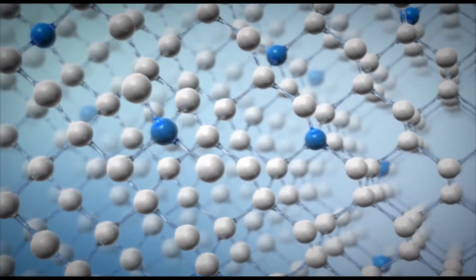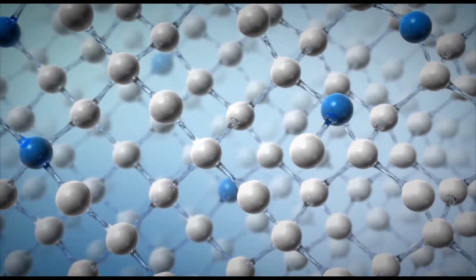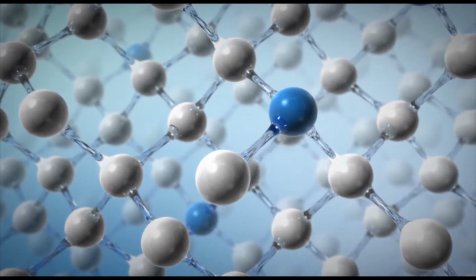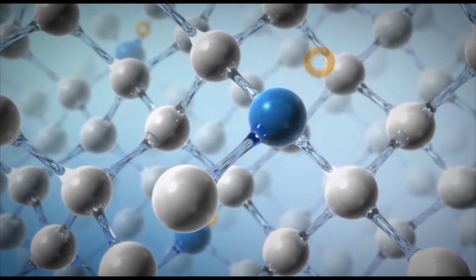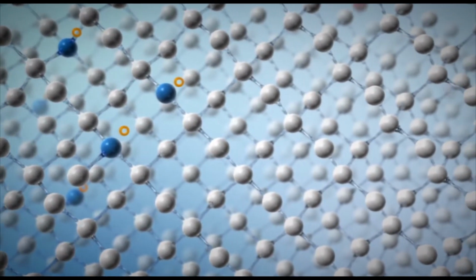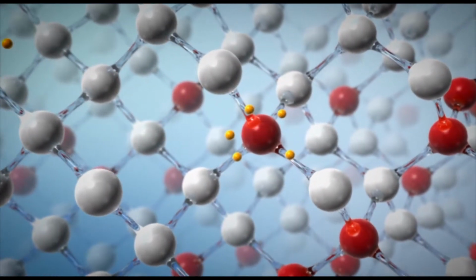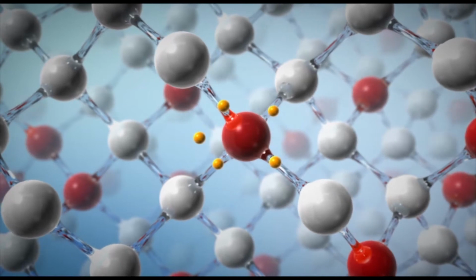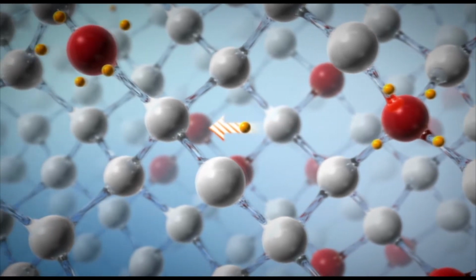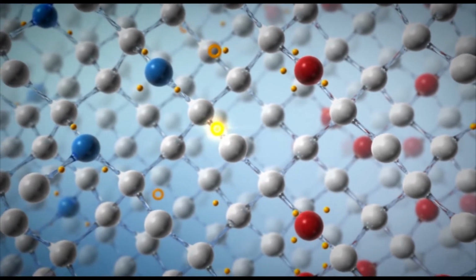The base material is silicon, which previously was mixed with boron atoms during crystallization. Boron is used because it has 3 outer electrons, one less than silicon. A positively charged hole is thus created in the atomic bond. Diffused phosphorus atoms are slightly different. They have 5 outer electrons, which means one more negatively charged electron than silicon. The result? 2 different charge carriers, negative electrons and positive holes, that strive to achieve an equipotential bond according to the principle of opposites attract.